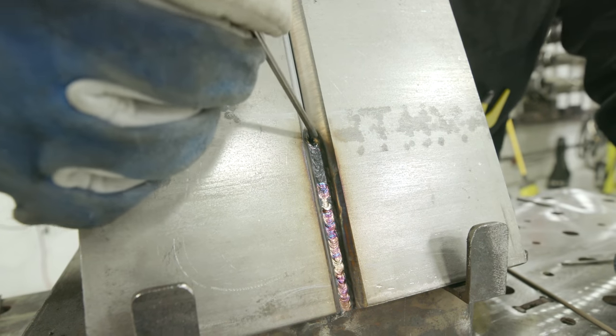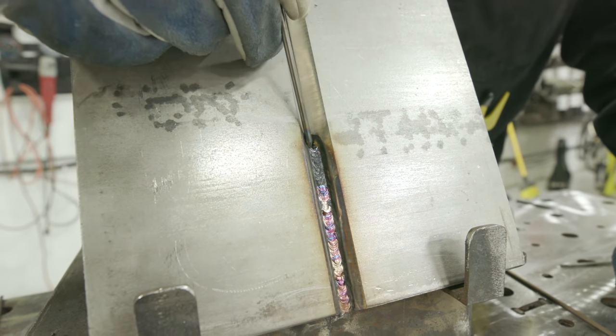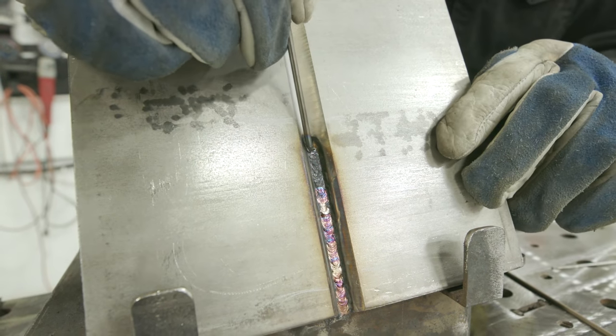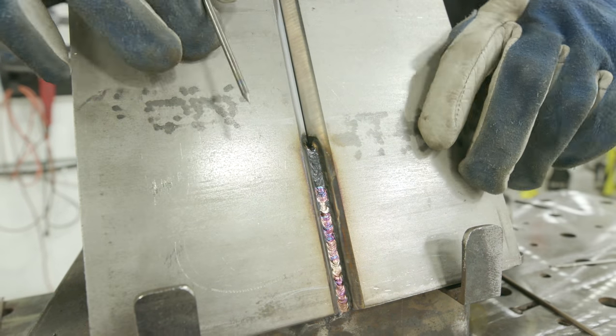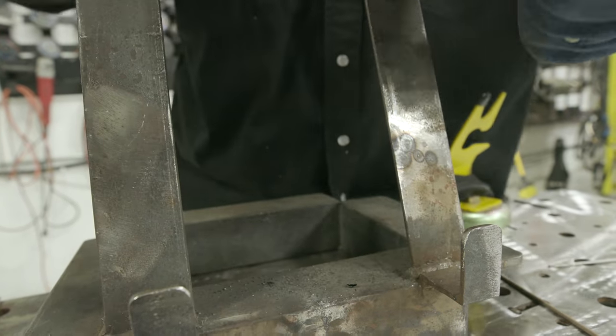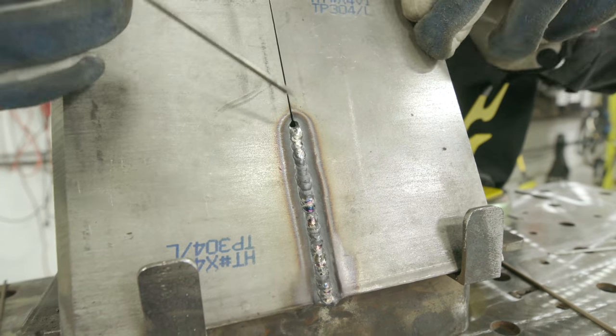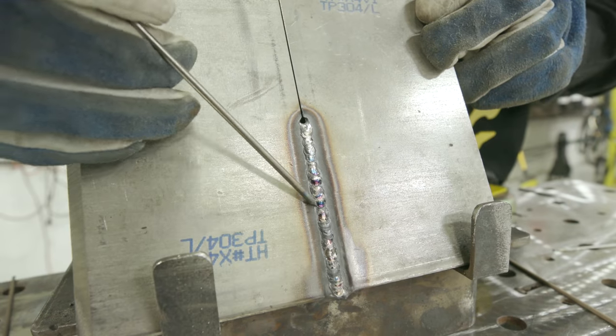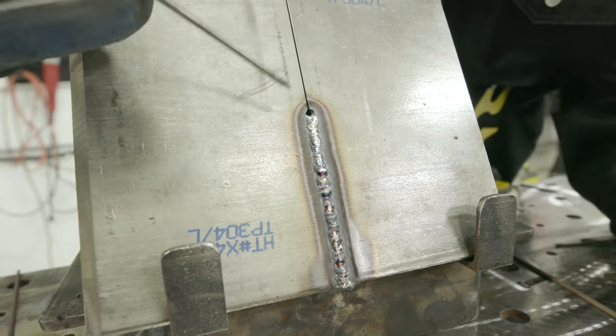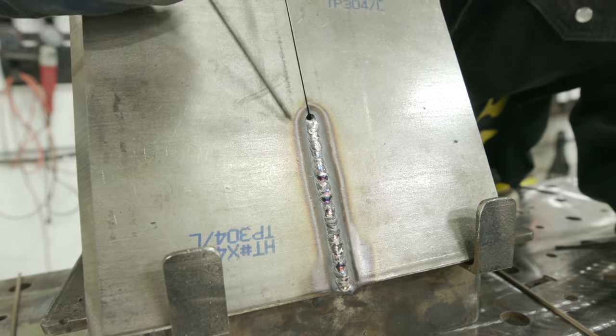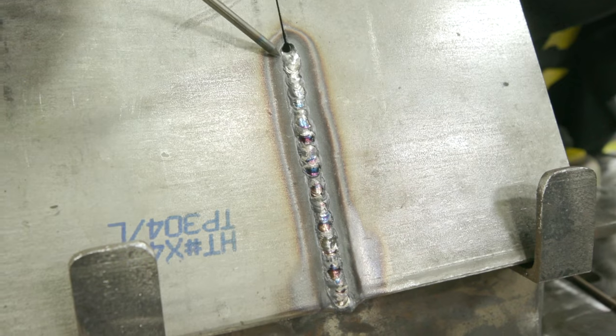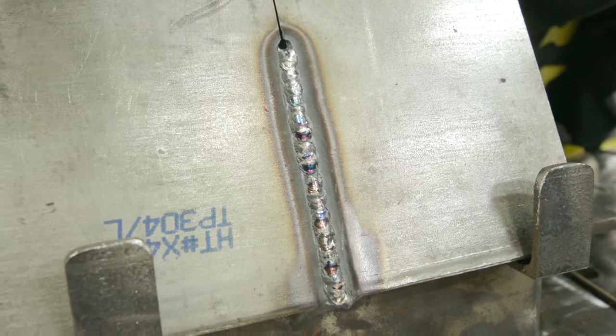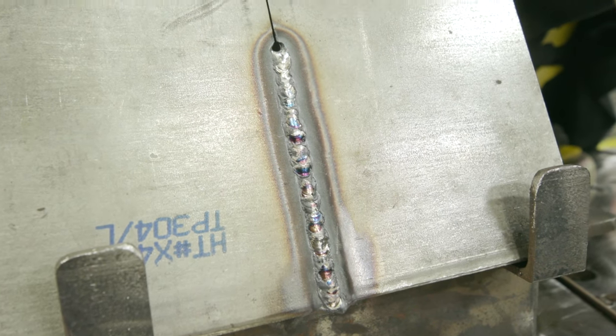We'll chip this off, get a wire brush or wire wheel. Flip it over - see how there's no sugar or nothing? This is coming off all nice in color. This is x-ray ready right now because I didn't dip my tungsten, didn't get no cold wire feed. This is good x-ray quality root. No undercut on the sides, no excess reinforcement, all under 1/8 inch.